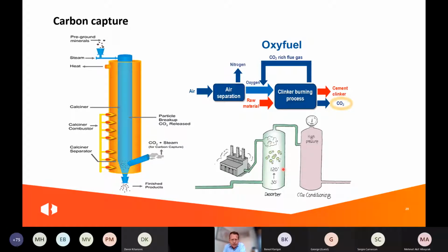And the third picture is using an amine solution to capture CO2. You can capture the CO2 from the gases in this amine solution, and then you can release the CO2 again by heating it up to 120 degrees, and then you will end up with pure CO2. And this type of carbon capture is going to be installed on a large scale in a factory in Norway. So these are only 3 examples.